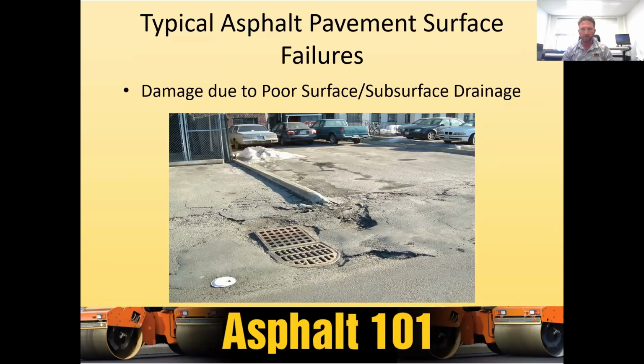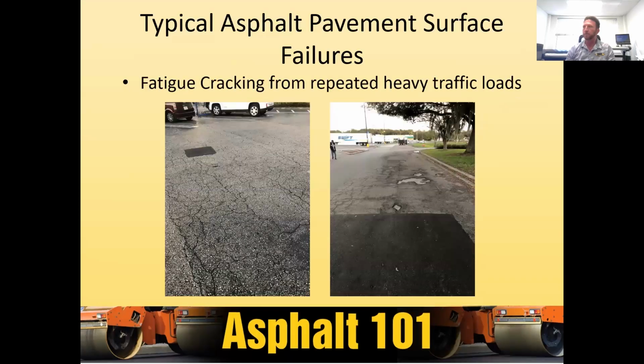If you've got an area in your community or in a parking lot that holds standing water a lot, go look at it when it's dry and you'll see fatigue cracks starting to form. You'll see asphalt failures. You'll see depressions and rutting in those areas simply because you're weakening the surface by leaving that water on the surface. Fatigue cracking due to repeated heavy traffic loads. Typically, that's what it's caused by. This is also called alligator cracking because of the shape that it makes. It looks like kind of the back of a gator.